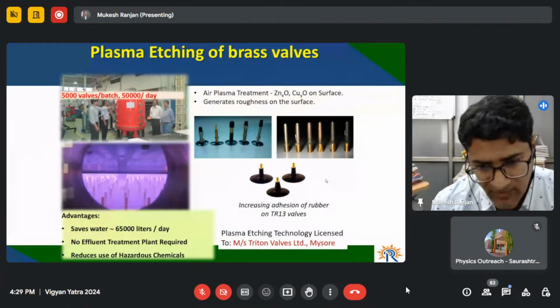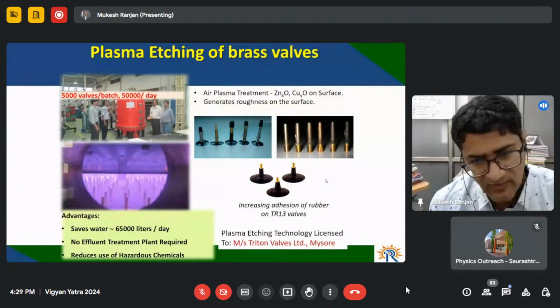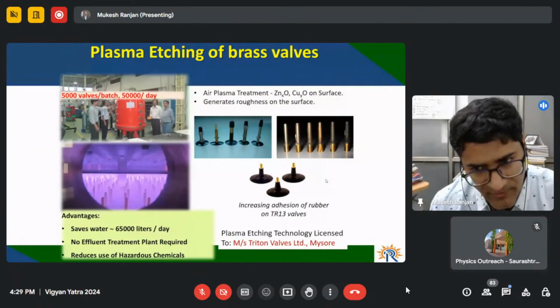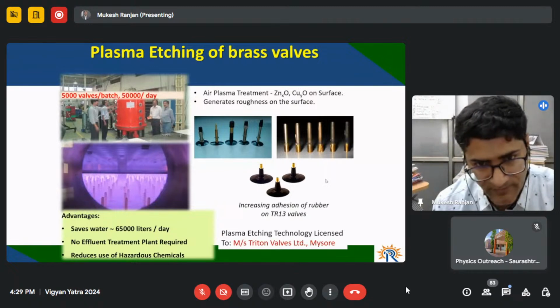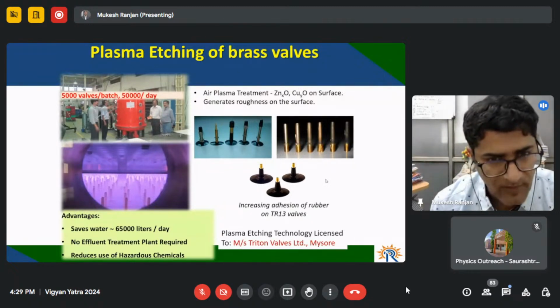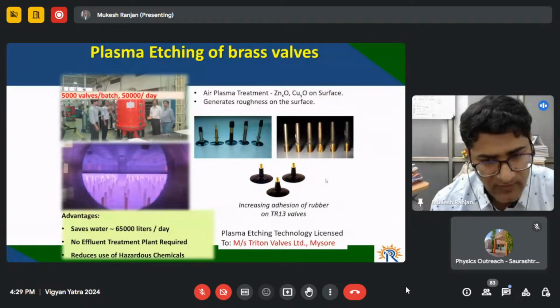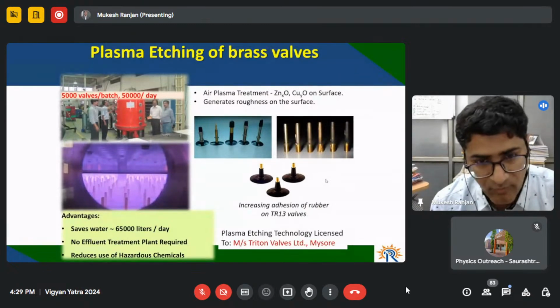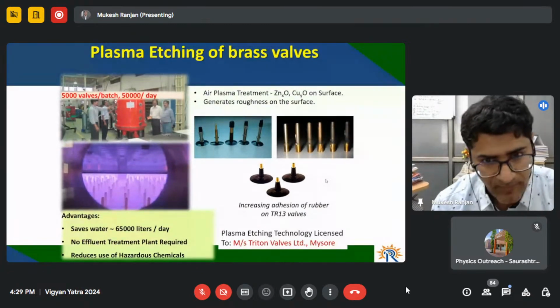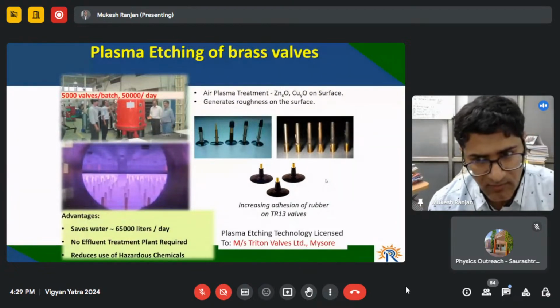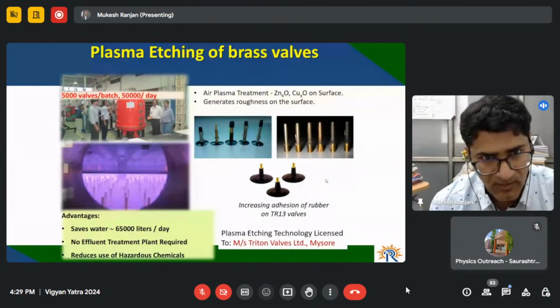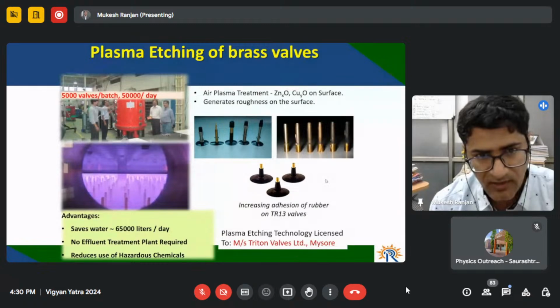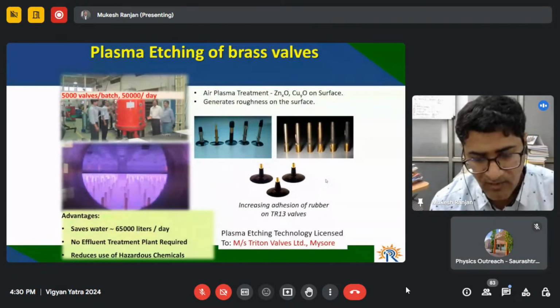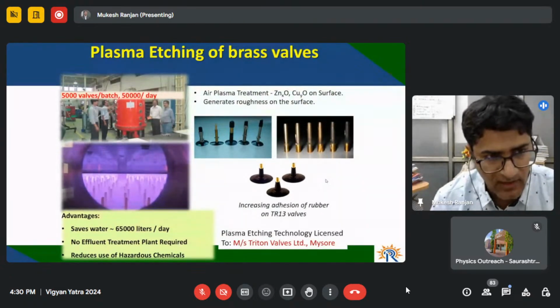When you have a sandpaper, these grit particles are separated by fractions of a millimeter or some hundreds of microns. But once you do the same process with plasma, you are bombarding energetic ions on the surface. So you are doing atomic cleaning. Emery paper does the cleaning at a micron or millimeter scale, but once you immerse something inside the plasma, you are doing the cleaning at an atomic scale. That's the reason plasma is a very good cleaner.